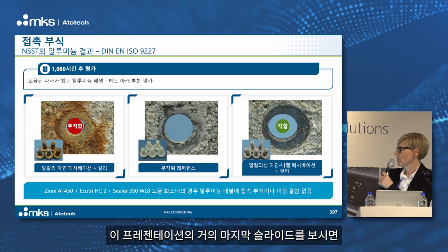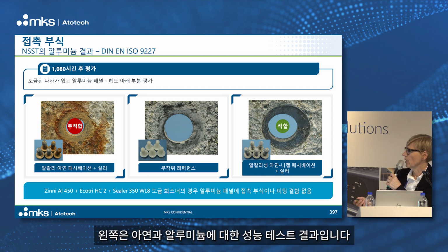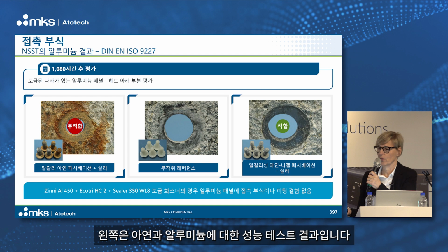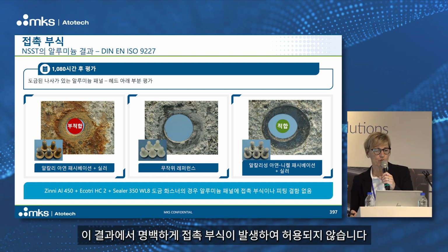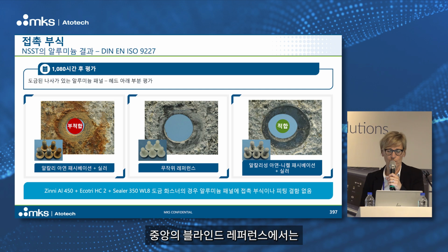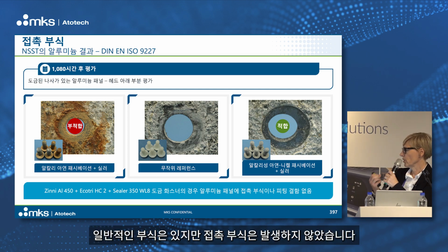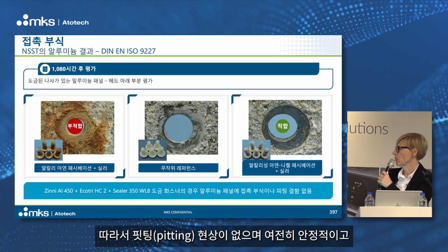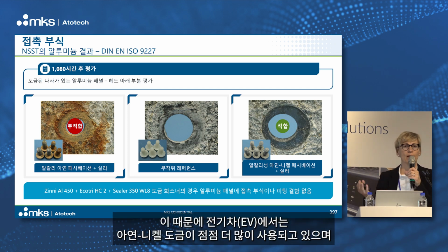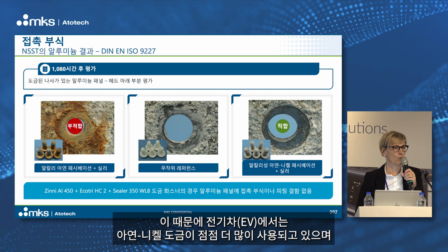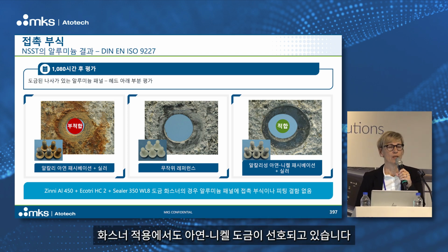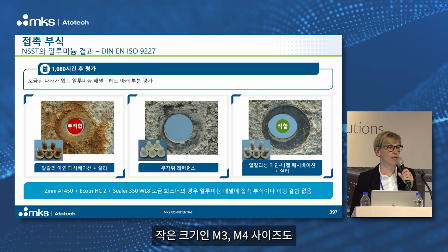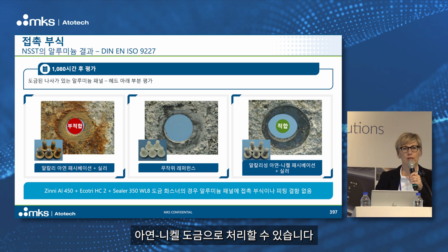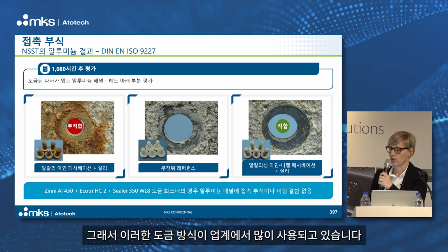Yeah, and if you are looking at this more or less last slide of this presentation, on the left is the performance of zinc and aluminium, and you see there is really contact corrosion, so it's not acceptable. The blind reference in the middle has just corrosion, but no contact corrosion, so no pitting, and it's still stable, and with the zinc nickel that is working. And this is why we are seeing much more zinc nickel now with the EVs coming. With zinc nickel you can also fulfill the small fastener sizes like M3, M4, and therefore we are seeing this a lot in the market.